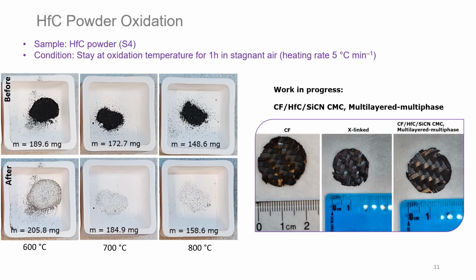The hafnium carbide powders were then oxidized in the presence of air for an hour at different temperatures, and they showed oxidation even at 600 degrees centigrade. This result is expected as hafnium carbide starts forming hafnia in the presence of oxygen at temperatures even at 500 degrees centigrade. However, when combined with silicon carbide or silicon carbonitride, hafnium carbide forms a phase which can deter oxidation at higher temperatures. So the next logical step for us is to use these precursors to fabricate a multi-phase hafnium carbide silicon carbide ceramic.